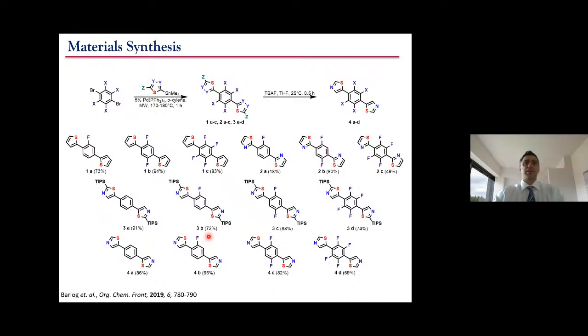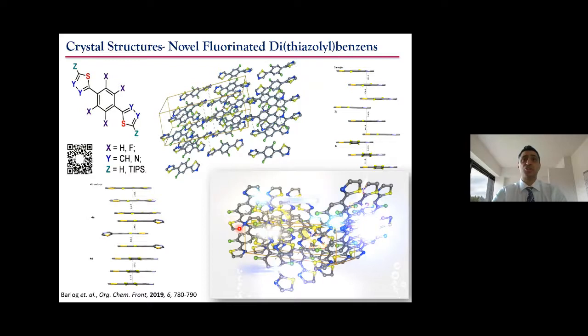So we come back to the aspect of having this to be direct aligned, or direct alignment as the project title was. So the idea was to put fluorinated parts on these systems, having a thiazole, having the thiophene, and having different groups. So Maciej managed to make about 15 different compounds. So again, pharmaceutical companies would love things like this. So we made 15 different compounds, and basically we managed to get even X-ray structures of these compounds in terms of showing their analysis. And it was published most recently in Organic Chemistry Frontiers.